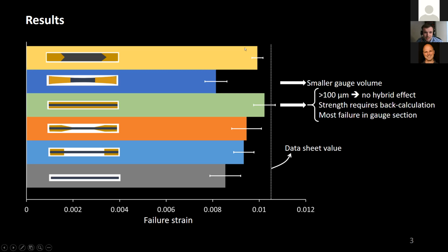But the benefit being here with this one, you can actually get strength directly, but we don't know whether the specimens actually failed in the gauge section. So this is certainly an interesting design to look at in further detail, because this is also much easier to use than the butterfly design or the continuous end tabs, where you need to either water jet or add glass plies on top and then do a back calculation.